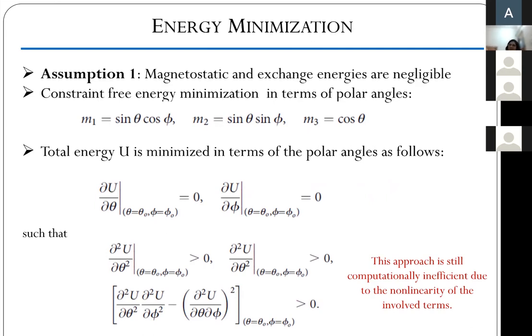we are getting rid of the constraint. Otherwise, we would have to do a constrained minimization and introduce an additional parameter. But still, given the nonlinearities involved in the terms, this approach becomes very messy. Also, because we are dealing with theta and phi, when we apply just the first derivative equal to 0, you get minima and maxima. There are a whole lot of solutions, and then we have to avoid redundancy. We have to make sure that we only pick thetas and phis within a certain range, 0 to 2 pi and 0 to pi and so on. And the sorting becomes a big issue.